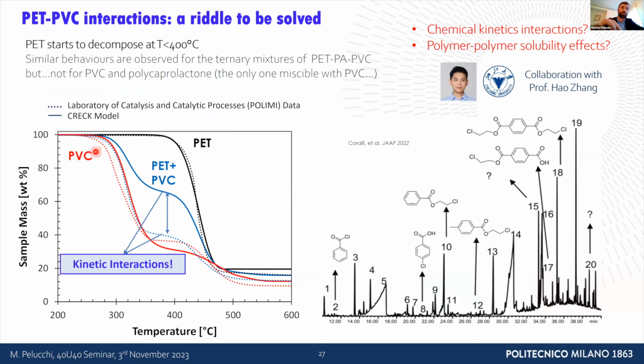What I'm showing here in this plot, in points, are the experimental measurements of PET and PVC mass loss profiles. In blue, you see the PET, PVC 50-50 mixture. If they worked as polyolefins worked, the model would be the solid blue line you see—a 50% decomposition of one and 50% decomposition of the other. In reality, once you put PVC and PET together, PET kind of accelerates, and the mass loss profile curve approaches that of PVC, like PVC is dominating this decomposition.